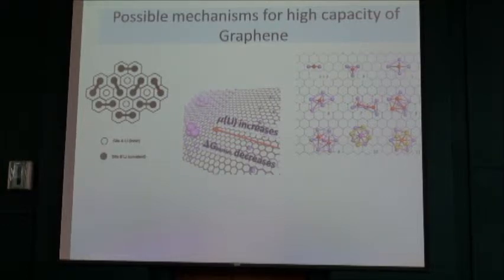You can actually explain this: typically when you have some lithium atoms decorated, the barrier, we call it the Gibbs barrier, is going to decrease. Otherwise, what happens is you put in more and more lithium and basically plate your graphite. It's what we call lithium plating. But if the barrier decreases when you have more lithium atoms, you don't really plate it. Then the electrochemical potential gradually increases. That gives you higher capacity. This is the theoretical explanation, but we have to do some more work.